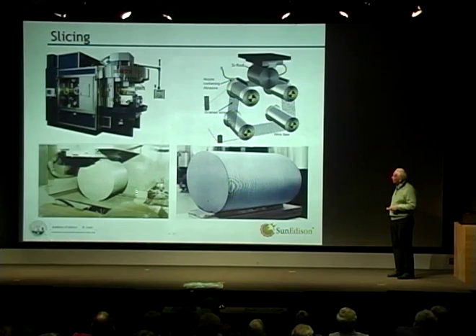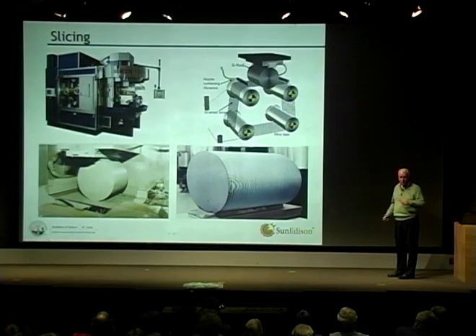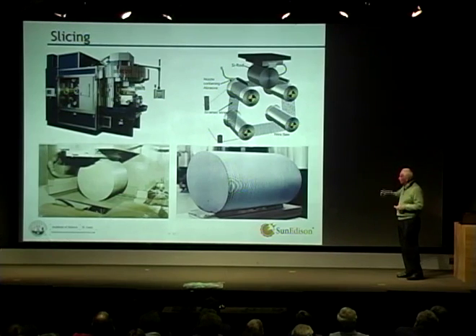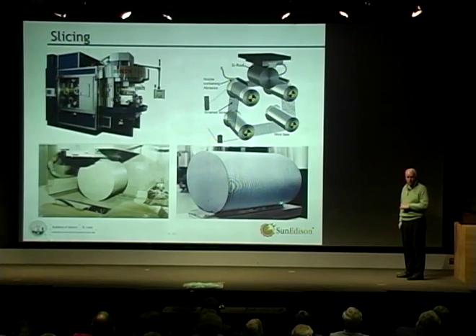And here's an actual photograph. That's a schematic. Here's an actual photograph. That's starting. Here's the web of wires. It doesn't look too clear because that's covered in slurry, and sometimes the slurry is joining the wires up. But when the crystal arrives, it'll go right the way through. And then here, this is the sliced crystal with the wafers still sitting on a carbon beam. Before doing this, you glue the crystal onto a carbon beam with epoxy resin, and so everything's held up there.